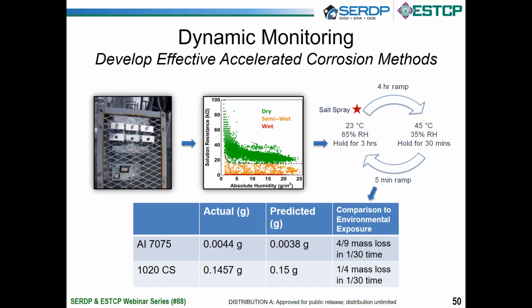So where this fits in the overall scheme of ACT development is we can use, like you see on the left, mass loss coupons along with our dynamic monitoring sensors. We can then analyze that data to capture the temperature and relative humidity cycling that we're seeing in the operational environment, what that means in terms of the number of dry versus semi-wet versus wet data that we're measuring, and we can use that information to inform new accelerated corrosion testing. And theoretically, this could be used based on geographical or different operational environments to design accelerated corrosion tests specific to the operational environment.